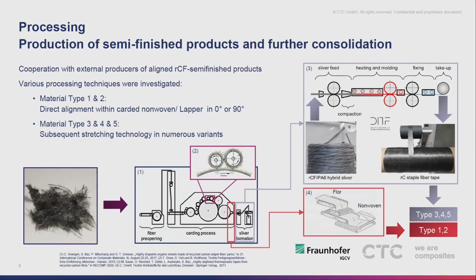In terms of practical purposes, we actually only had two major categories of alignment technologies to assess. The one is carding technology, where we work with a carded non-woven, which is then a little bit oriented through basically a kind of combing process in the carding. And the other one is a version of producing a yarn or a carded veil with a subsequent stretching process for increasing the alignment. But all in all, we always produce a pre-textile, which is basically a slightly aligned carbon fiber textile, either wide width or in a small sliver width. And then we use it either directly or we subsequently do additional stretching. Those are basically the main differences in the materials we have assessed.